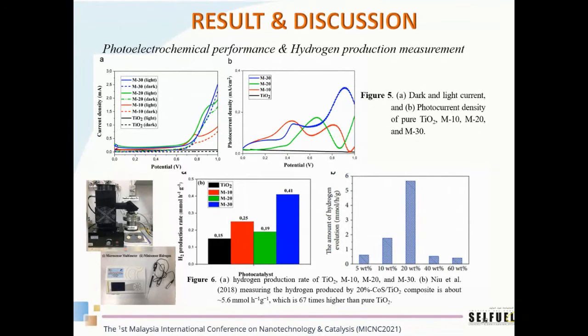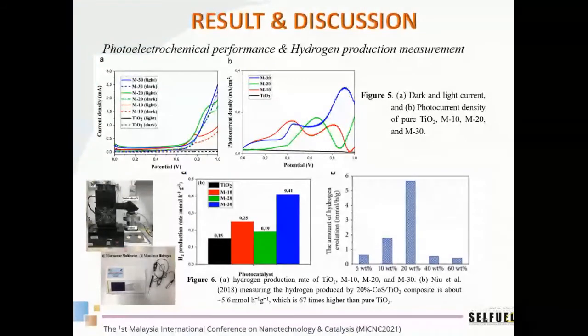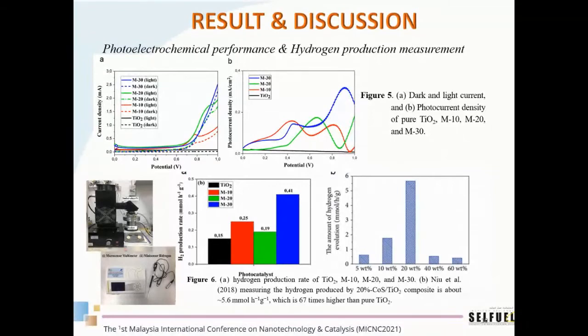The highest hydrogen production rate of pure TiO2 is about 0.154 millimole per hour per gram. Meanwhile, the highest hydrogen generation was obtained by the M30 sample, with a hydrogen rate of about 0.41 millimole per hour per gram. It's about 3 times higher than pure TiO2. If we compare to the similar study reported by New et al.